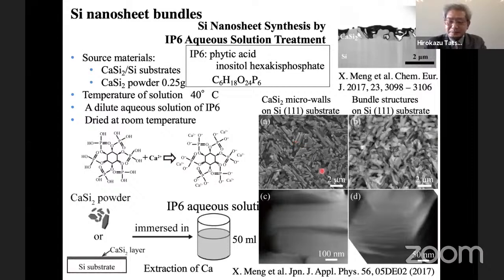So after calcium extraction, this domain structure remains, and in the domains such layer bundles are formed. The layers stand on the surface, not parallel to the substrate surface, but nearly perpendicular to the substrate surface.